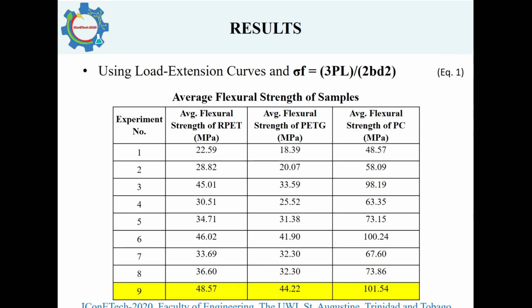The machine produces a load extension curve, which gives you the maximum force and the extension at which it occurs, using the formula in equation 1, where sigma F denotes the flexural strength of the sample at the midpoint, P represents the point load, L is the support span, B the beam width, and D the beam depth of the sample. This formula is used with the maximum load to determine the maximum flexural strength of the samples.